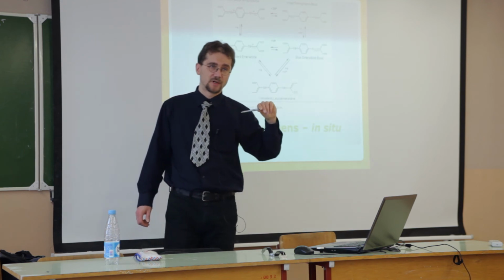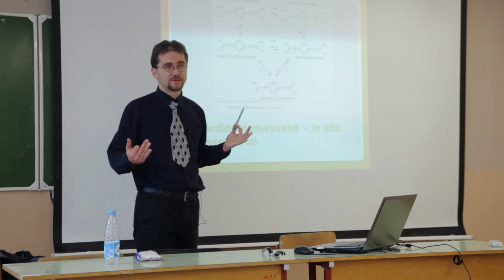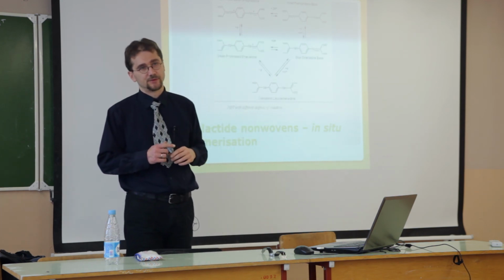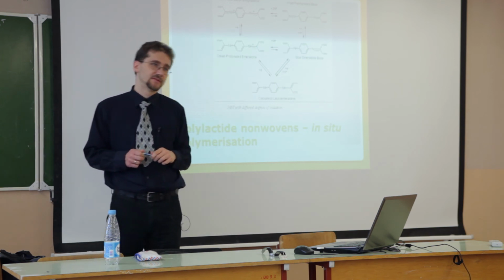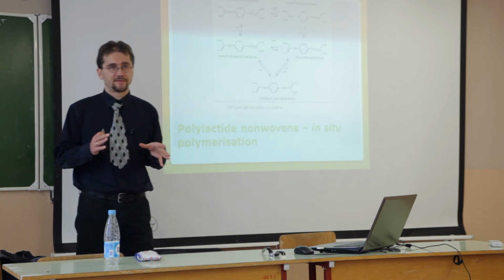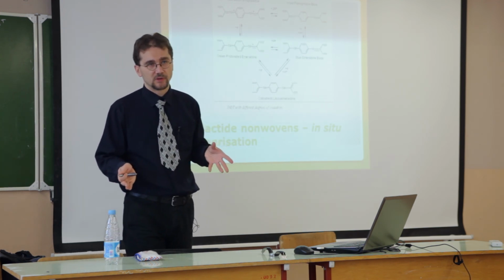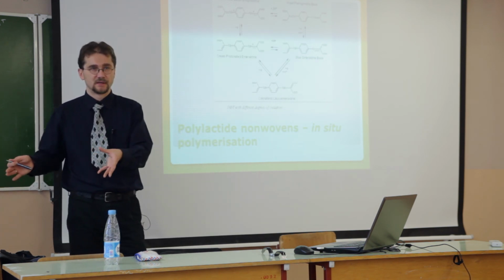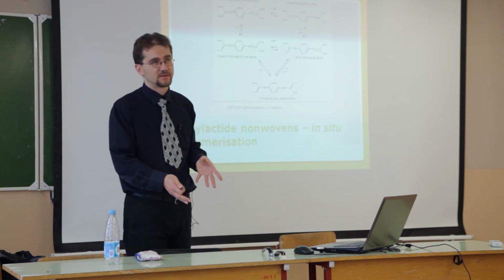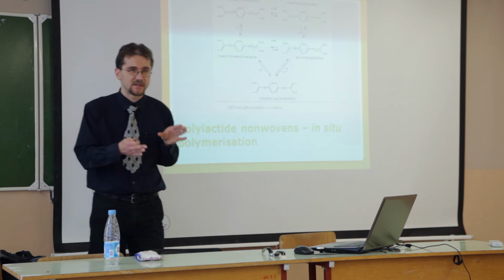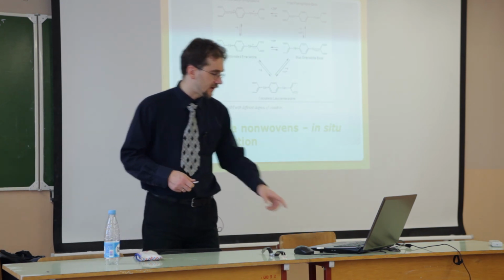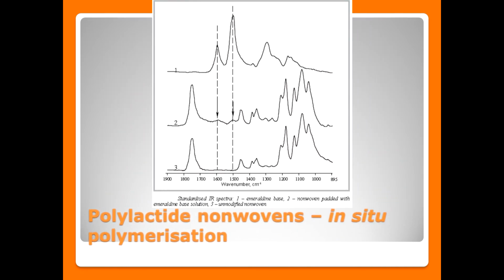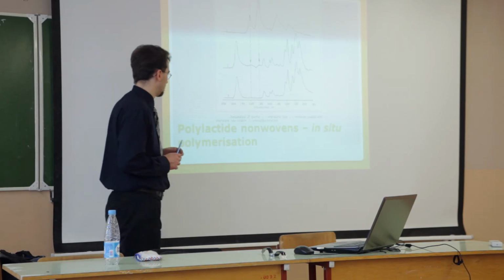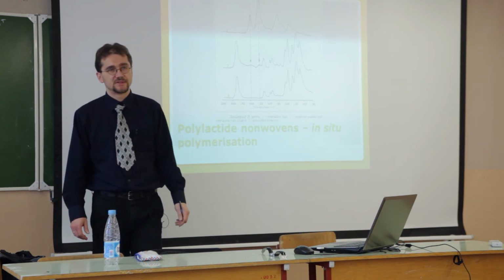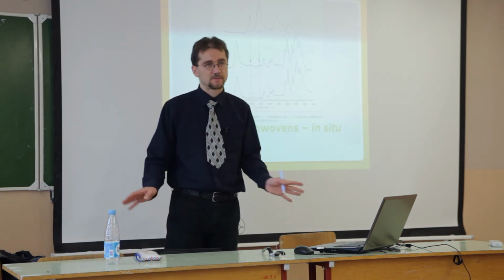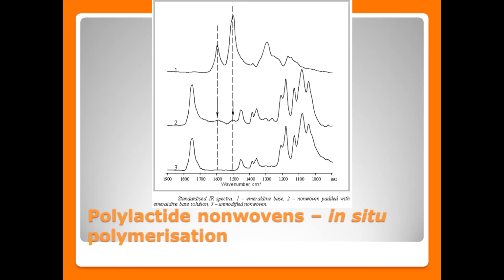We have different structures of polyaniline, and finally the material looks different, and it's difficult to deposit polyaniline on the surface. But we found a method - I would say a next method. We put our material into the monomer and start polymerization on the surface. This is not polymerization in some separate glass next to our material, but in situ polymerization on the surface. The effect was very nice. We controlled the structure of the material using standard transmission FTIR spectroscopy, which is a basic analytical tool for us.